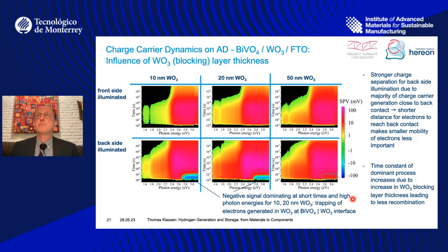So, for example, we can say that the stronger charge separation for backside illumination helps us, gives a shorter distance for electrons to reach the back contact, and gives the kinetics a better chance, and reduces the losses, because in bismuth vanadate, electrons have smaller mobility as compared to positive holes, and therefore back illumination for this material is better. But this is just one conclusion.